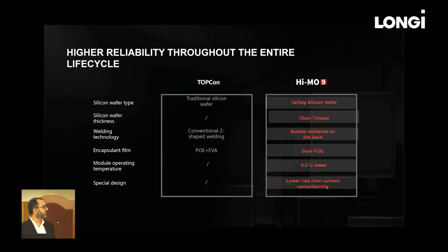So a summary of the comparison between TopCon and Hi-MO 9. First of all, as mentioned, silicon wafer type. We are using the TaiRay silicon wafer. Thickness, we have increased up to 10 micrometer. Welding technology, the I-type welding instead of conventional Z-type welding. Encapsulation changes from POE and EVA to dual side POE.